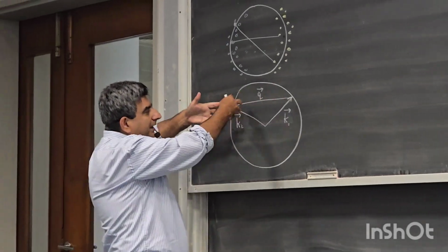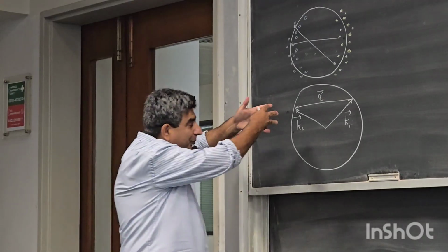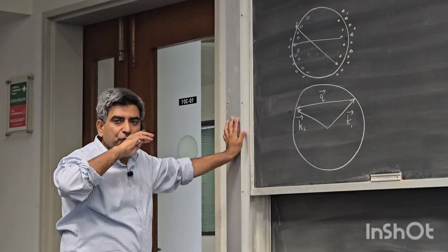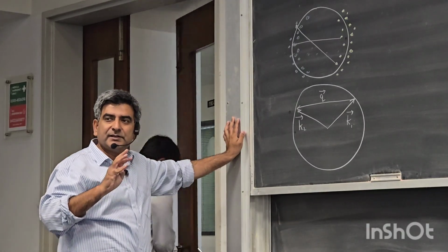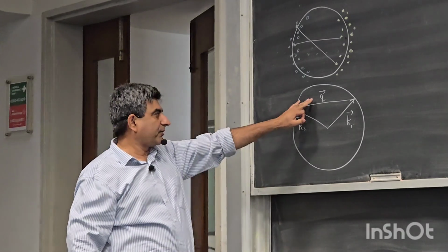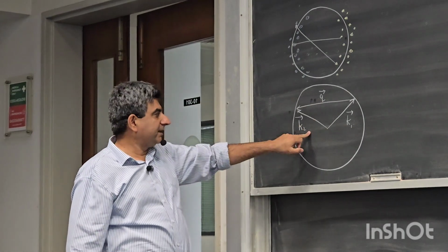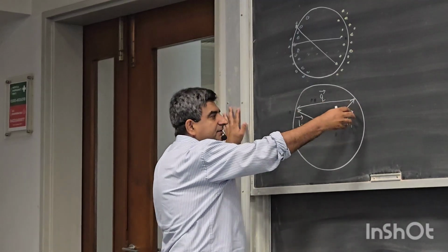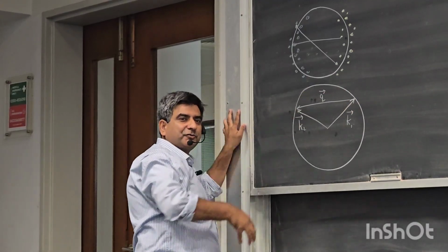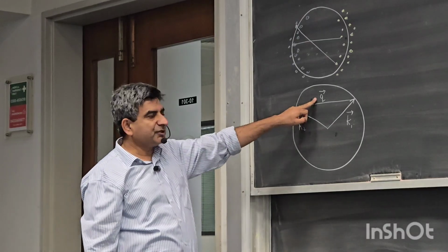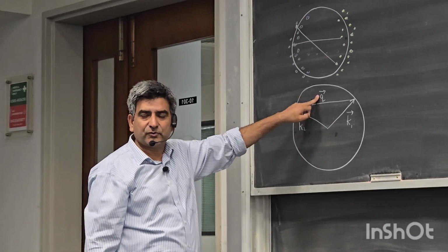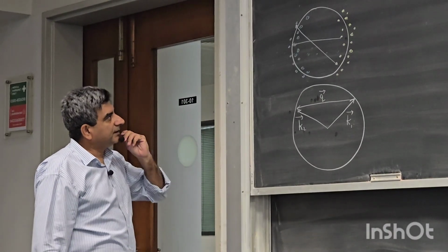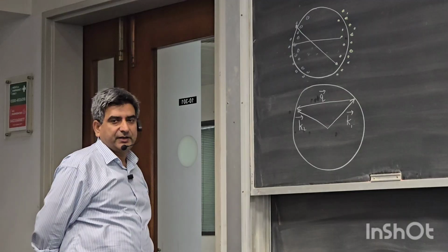So such a long wavelength is required. A long wave vector for the phonon is required. So this can only happen when the phonons have a wave vector of the order of q, which is the difference of k2 and k1. And this q is long enough that it spans from the right side of the Fermi sphere to the left side of the Fermi sphere. And corresponding to each vector of the phonon, there is a particular energy. So this is the mechanism for electrical conductivity.